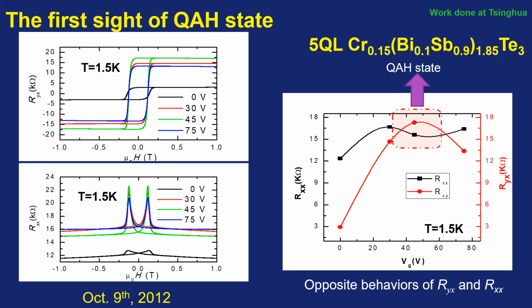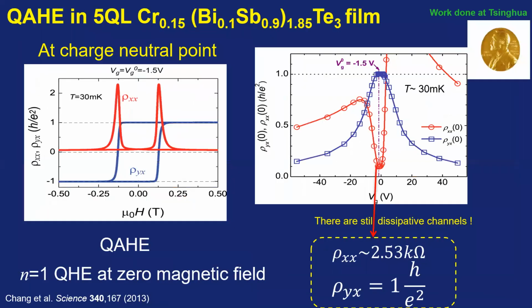This measurement is at 1.5 Kelvin, so we tried the dilution temperature measurement, and finally in this 5 quintuple layer chromium doped bismuth antimony telluride sample, we were the first to achieve a very nice quantum anomalous Hall state. This is at the charge neutral point. We can see the magnetic field dependence of the longitudinal resistance and Hall resistance. At 30 millikelvin, the Hall resistance is quantized and the longitudinal resistance is approaching 0.